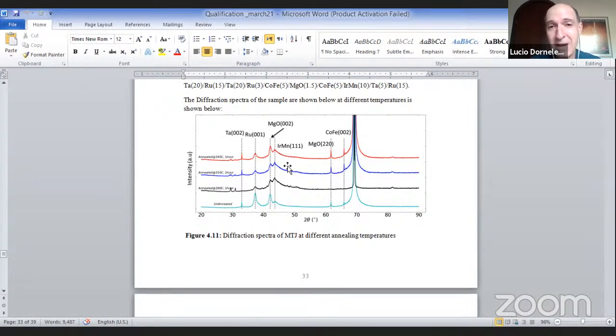But I think it may be the reflection from the silicon, the one at 69 point something. So this could be the K beta radiation. This may be the peak from silicon with the K beta component of the radiation, because you cannot kill it 100%. You have to check, but I would guess this. And maybe it's the same for the other small peaks. But anyway, I'm sure that the peak at 60 is not the 220, because it could not be so thin or so sharp. The width should increase at higher angles, not decrease. Okay, that's one.